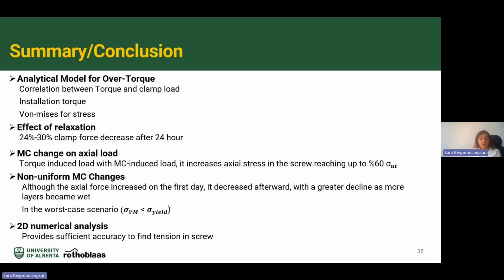So, based on what we found, due to moisture content change and non-uniform moisture content change, which happens inside the wood, the axial force increased on the first day, and it reached its peak. But afterward, it started to decrease, and there was a greater decline as more layers were exposed to water. In the worst-case scenario, we measured the stress on self-tapping screws, and it was less than the yield strength of self-tapping screws. And finally, we could develop a model by which we could find the axial stress in self-tapping screws.